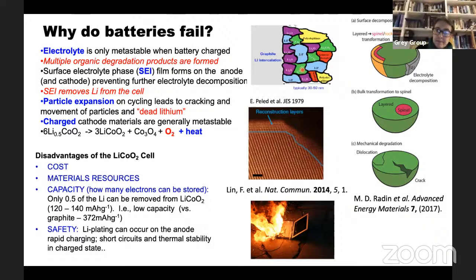But this passivating layer has to stop the electrons going through, but it has to still allow the lithium ions to go through. And so if you, for example, use your mobile phone in too hot environments, or you insist on using your laptop on your lap, which I'm doing right now, then this SEI degrades, and you start consuming more electrolyte, and you build up internal resistance as well, and so gradually the battery fails. So that's a major mechanism.